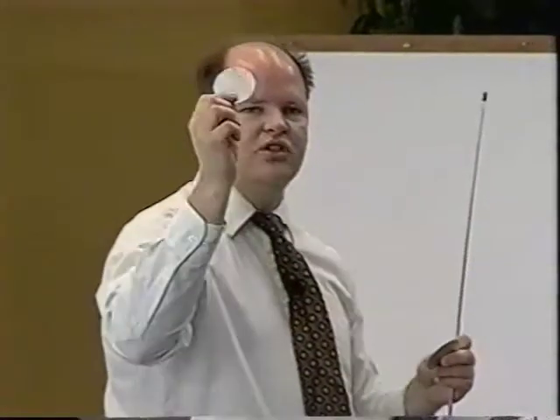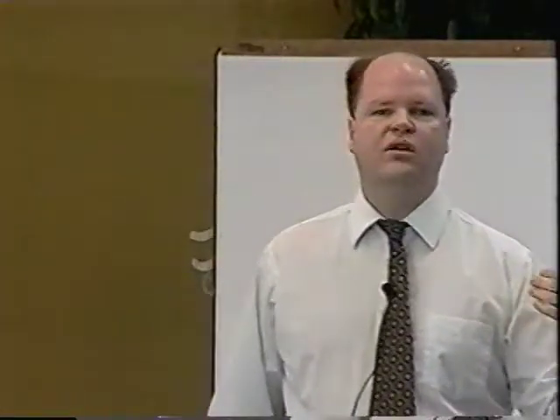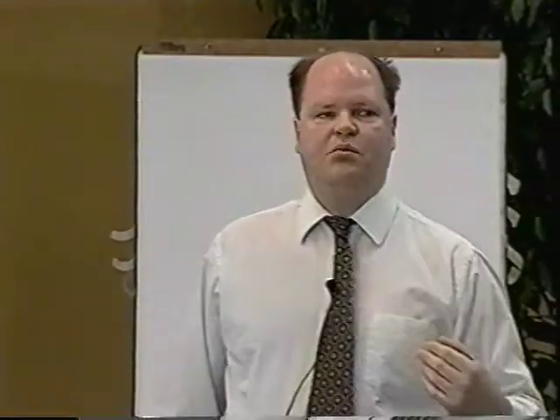I have a sample. This is actually a sample of our Burns Harbor product here, and another one of the Lackawanna. Watch out on some of the edges of these, they're a little bit sharp. But you can see the Lackawanna sample doesn't have the spangle anymore. About 2 or 3 years ago, they went to a no-lead pot also. So they no longer produce that type of product, but it's nice to have because that's a good starting point to understand zinc. But as you'll see when the samples come around, it's a nice smooth coating now. It doesn't have the spangled look.